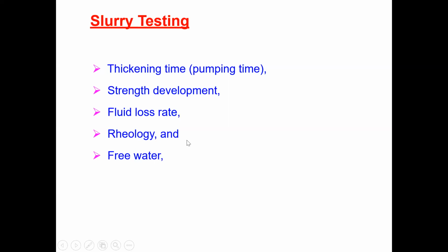Rheology is very important. Your yield point and everything has to be measured. And the free water I mentioned in my first class. Free water is the water that separates from the cement slurry when you keep it for some time. Maybe free water will be there. 1.4% is permissible for normal slurry, 1.4%.